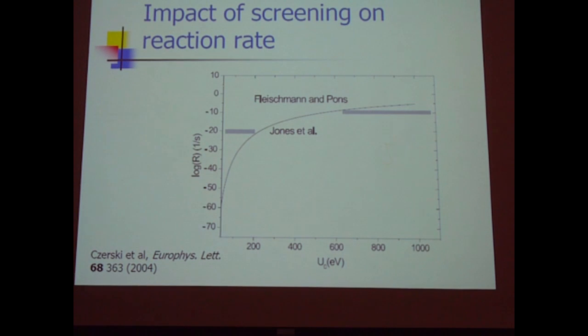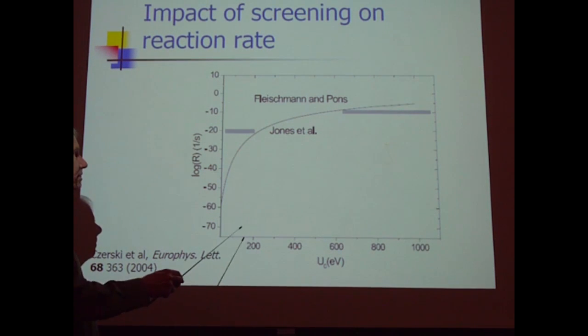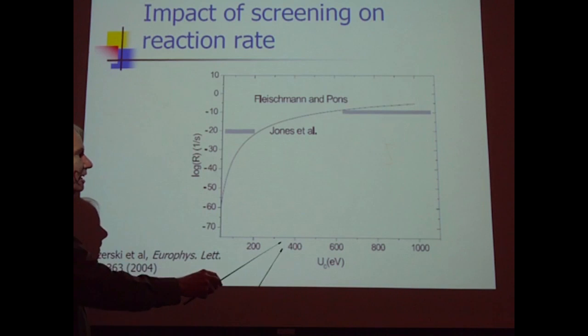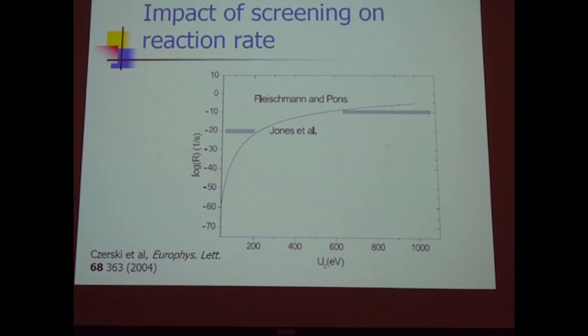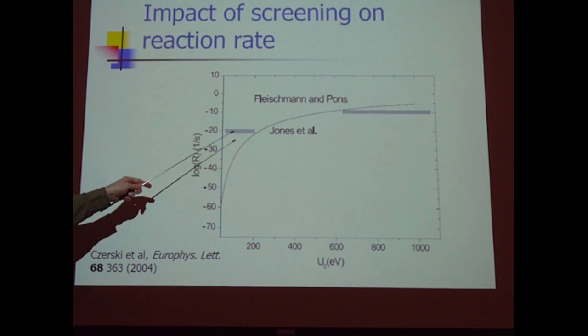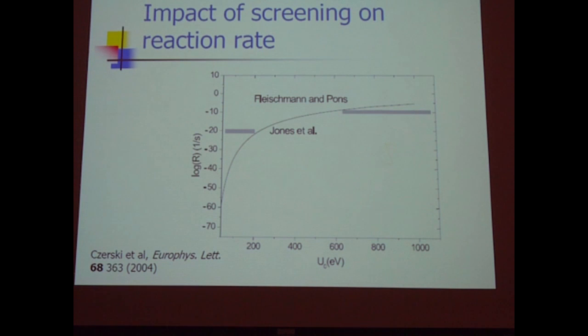So some people have said that the low-level fusion effect seen by Jones is due to screening. Now there's experimental evidence in low-energy beam experiments for there being a lot of screening. So they're saying, well, maybe the low-energy emission in the experiments could be explained by that. I'm very skeptical of that, mostly because Baranowski did some diamond anvil loading experiments. He put a lot of deuterium into palladium, had a neutron detector in, and didn't see anything. And if you actually had screening of this magnitude in real life, then he should have seen neutrons coming out, but there weren't neutrons coming out.